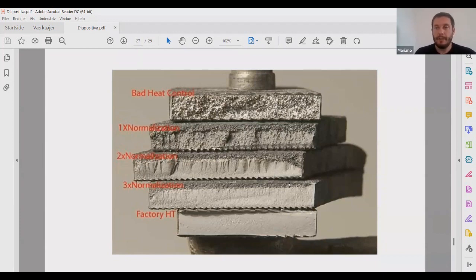So the next step after quenching in oil is the tempering process. We are going to clean the edge and we need to temper the blade as fast as we can. I'm going to use the forge and I want to use always the edge going up to heat very slowly. I'm going to start with the bolster area, and when I get close to the right color, I'm going to start to move very slowly to the tip to get all the blade at the right temperature. Because I normally do traditional blacksmithing, I don't want to use a heat treat oven, but of course it's the best option if you have one. For this type of knife, I'm going to use the straw color.